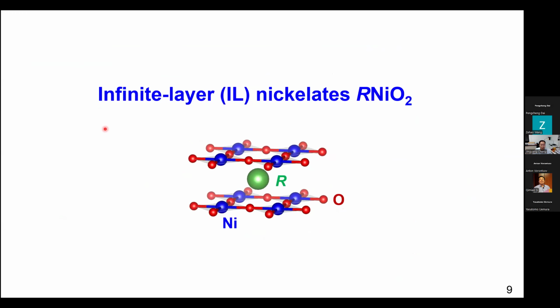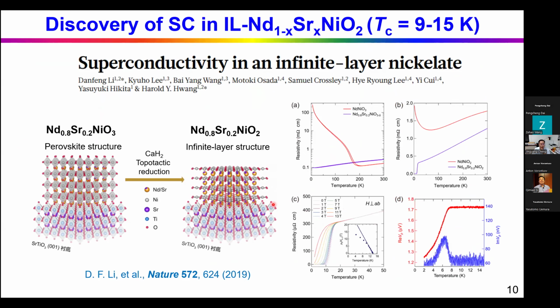So I think with this basic knowledge, we can move on to describe the recent experimental progress on the nickelate superconductors. First, I will show the result on the infinite-layer nickelate, this 112 phase. In 2019, the Stanford group led by Professor Harold Hwang reported the discovery of superconductivity in infinite-layer nickelate. This is the strontium-doped, hole-doped neodymium nickelate 112 phase. This 112 phase is obtained by topotactic reduction of the corresponding perovskite 113 phase, just removing the apical oxygen to get this infinite-layer phase.